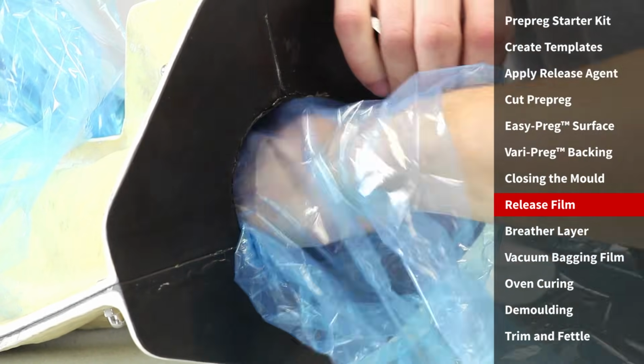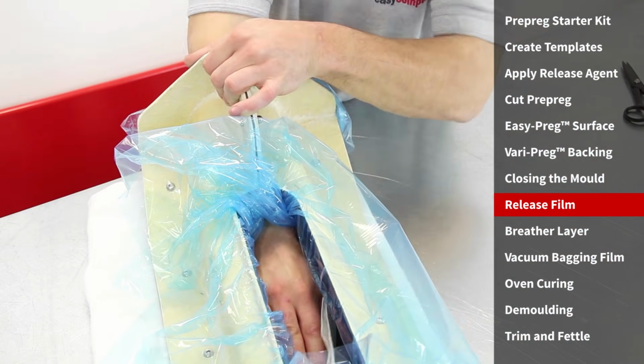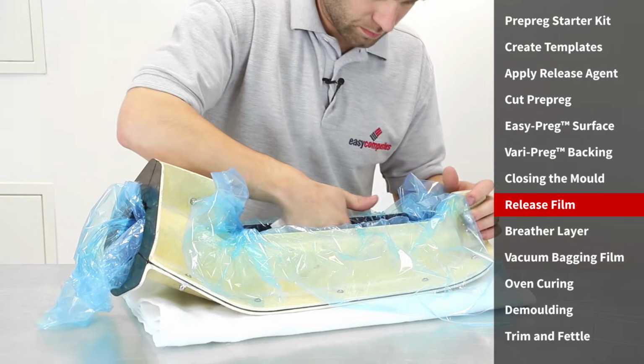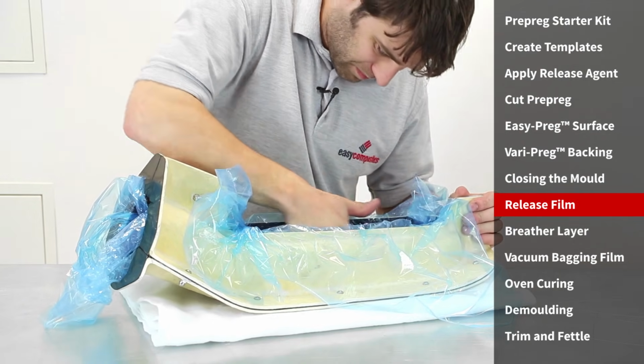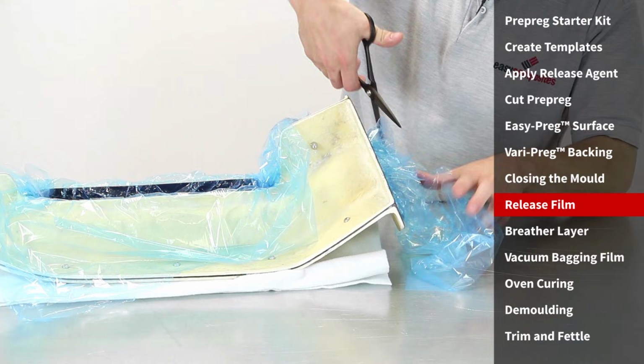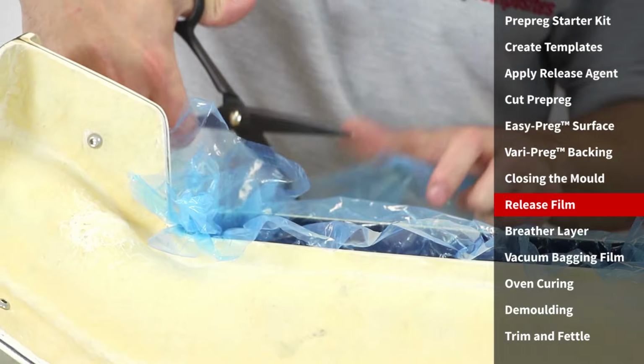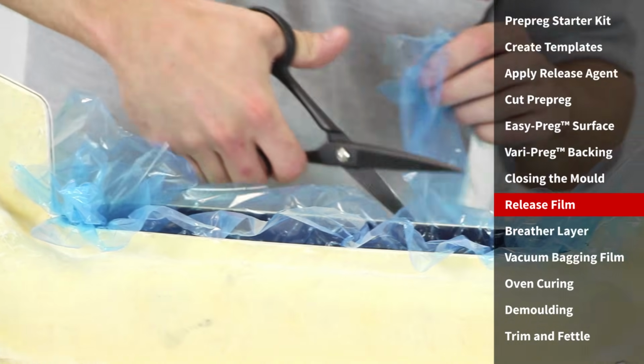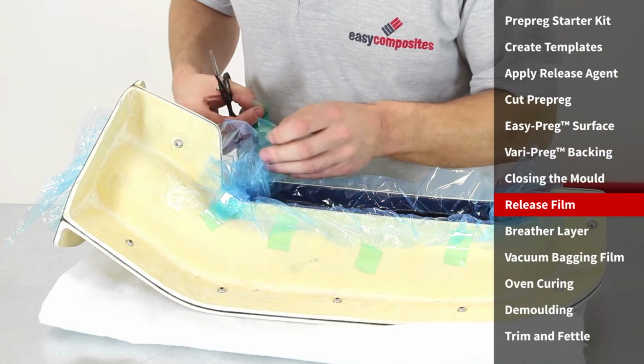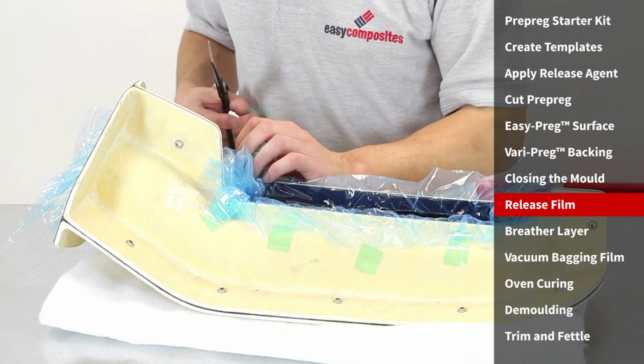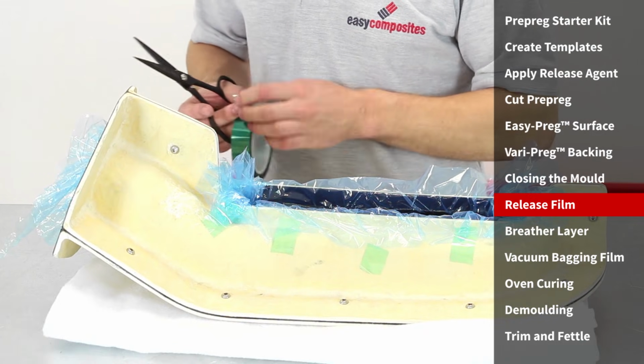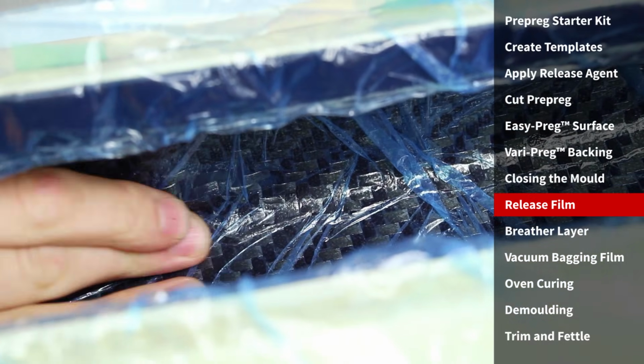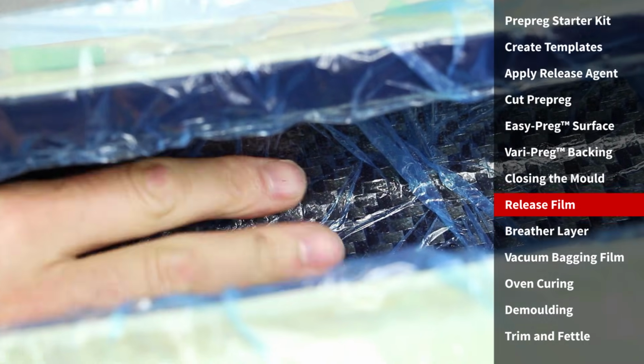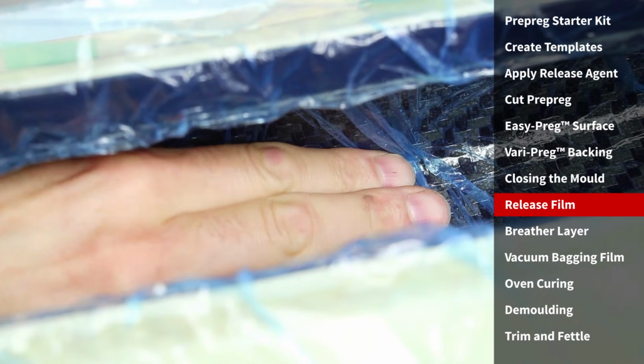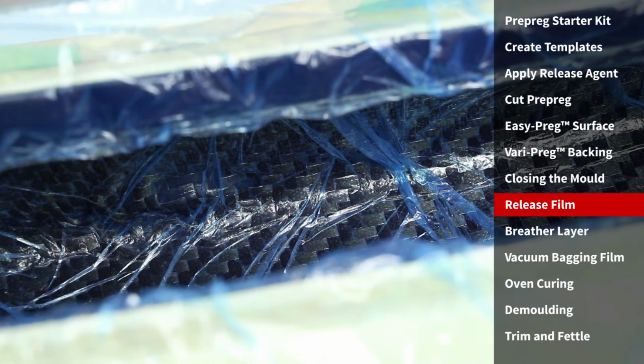The purpose of this release film is to provide a non-stick, impervious barrier between the pre-preg material and the breather layer which we will be adding next. Pre-pregs have perfectly measured resin to fibre ratios, and so we don't want the breather to absorb any resin from the laminate, which is why we always use unperforated release film with these pre-pregs. Ensure the film covers the whole surface of the part without any tight spots or bridging, using some tape to hold it in place. Don't worry about overlaps and creases, as these will not have an adverse effect on the part. Check again carefully for any bridging, particularly in the corners.